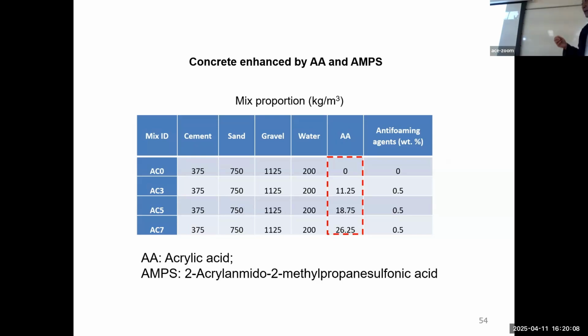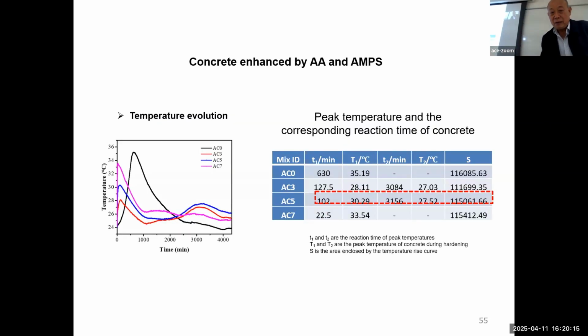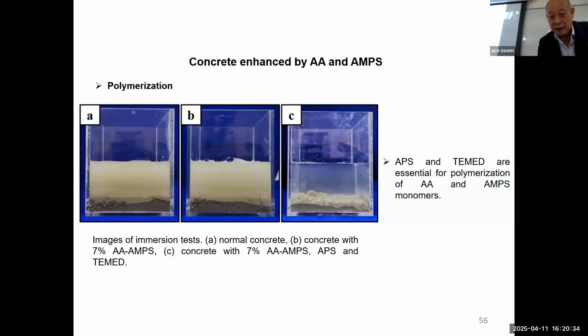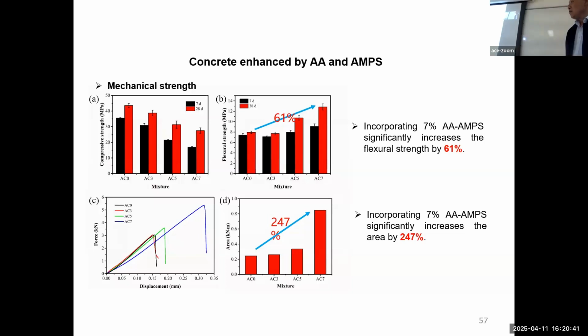and one of my students, right now in Singapore, did it for concrete, also using the same technique with this monomer. What I found very interesting is that by adding this monomer, the hydration heat history is also different. The peak is lower than the reference specimen. And then after the reaction, the water is very clean. And then we checked the fracture strength. The best one can increase about 60% for the concrete, and the toughness can increase about 247%.